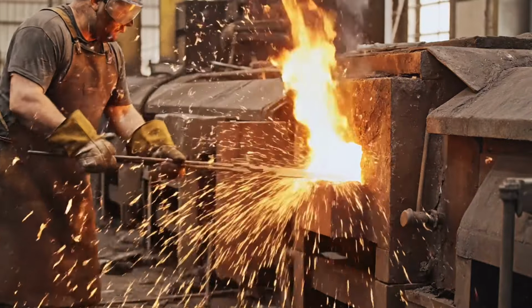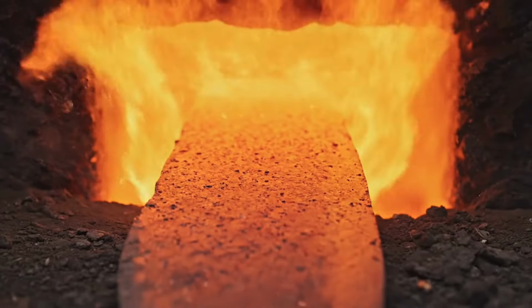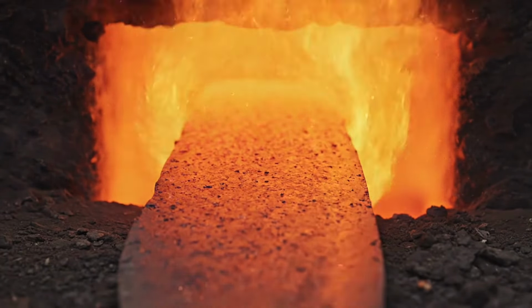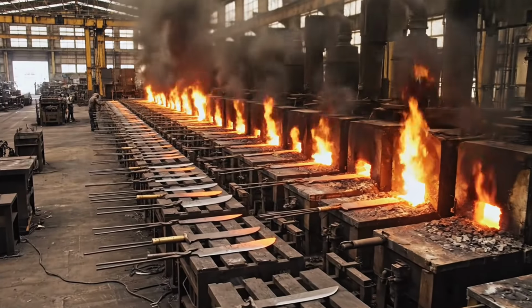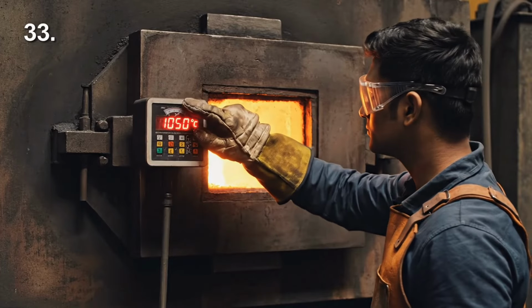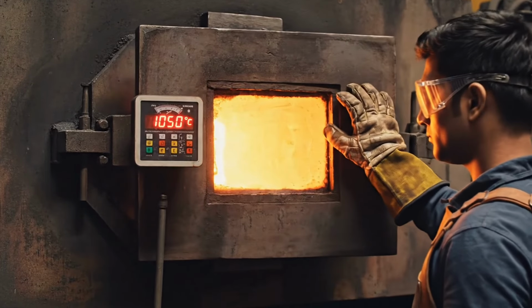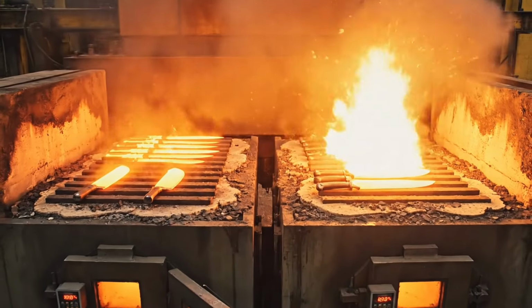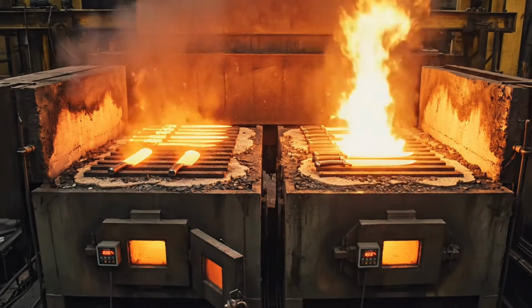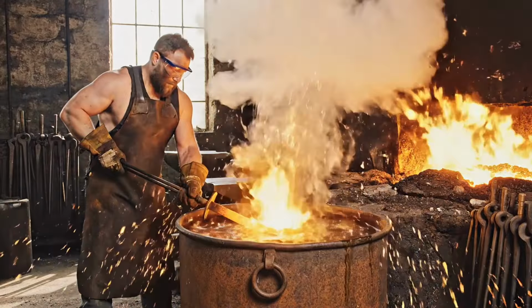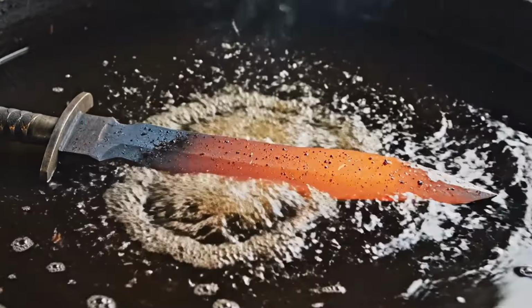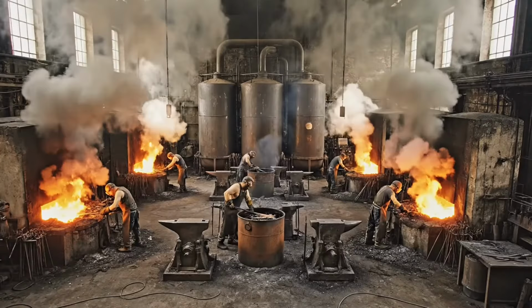The blade enters a high-temperature furnace, beginning the precise heat cycle that determines its final hardness and durability. During heat soak, the blade remains at a steady temperature to allow carbon to redistribute evenly within the steel. When the blade reaches the ideal heat, it is removed quickly and plunged into oil to lock in hardness through